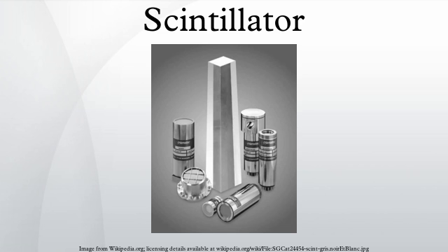Gaseous scintillators have also been used in nuclear physics experiments. Electrons. The detection efficiency for electrons is essentially 100% for most scintillators. But because electrons can make large-angle scatterings, they can exit the detector without depositing their full energy in it. The backscattering is a rapidly increasing function of the atomic number Z of the scintillator material. Organic scintillators, having a lower Z than inorganic crystals, are therefore best suited for the detection of low-energy beta particles.